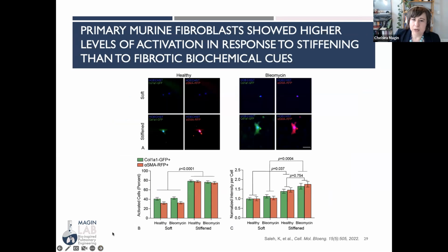Again, we used our primary mouse fibroblasts that have this dual reporter system, and we saw that levels of activation in response to stiffening were higher than they were in response to just biochemical cues alone. So the data in the graph down here shows the percent of activated fibroblasts when grown in these microenvironments. You can see on the soft hydrogels, whether they're healthy or filled with decellularized extracellular matrix from a fibrotic mouse, their levels of activation are relatively low, around 40%. Upon stiffening, the levels of activation for both of these microenvironments increases to about 80% with no significant differences.